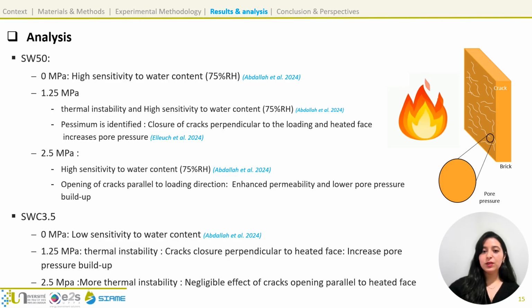For SW50 at 0 megapascals, the brick shows high sensitivity to water content, with instabilities occurring at 75% relative humidity. At 1.25 megapascals, thermal instabilities are again observed with a pronounced sensitivity to 75% relative humidity. Here, a pessimum is identified where the closure of cracks perpendicular to the load and heated face leads to a buildup of pore pressure. At 2.5 megapascals, sensitivity to water content remains high, but the opening of cracks parallel to the loading direction enhances permeability, releasing pore water and reducing pore pressure, which minimizes the spalling.